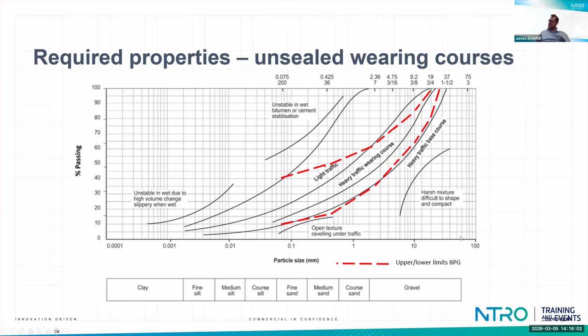So at this end, we've got coarser materials, so at the top end, we're talking about materials that are around, I don't know, 25, 30 millimeters in size. And all the way down, once we're getting down at this end, we're talking about very fine materials. And there's a general rule of thumb at the bottom of this picture showing that we've got gravelly type materials at the larger particle size, moving through coarse sands to fine sands down to silts, and at the very small particle sizes, the passing 75 micron, etc., the clay type materials. And typical road materials are made up of a gradation of different particle sizes, and the red line is showing a typical grading envelope that we might be operating in for unbound granular materials.